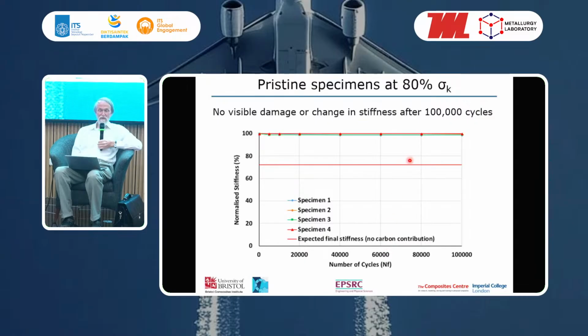So initially, when they were fatigued at 80% of the knee point strain, there was no damage. 100,000 cycles at 80% of that knee point strain, no failure of the carbon, no damage at all.